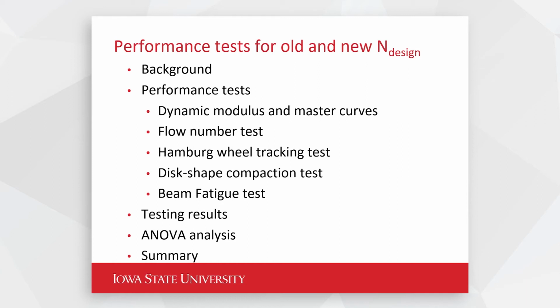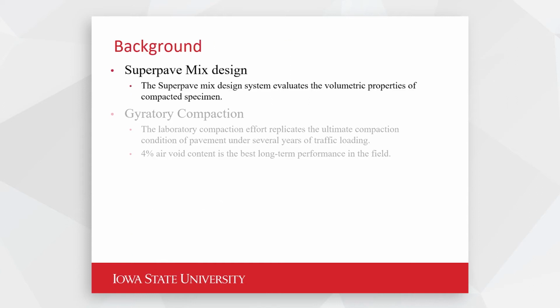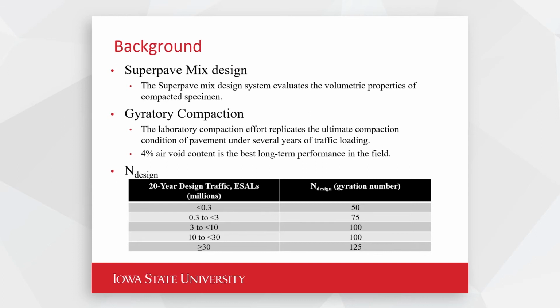And then after that, we were doing some pavement ME. So we won't go into all of the details of how we attain the optimum binder content and all that. That's fairly standard at this stage. But what we can do on the next slide is highlight the new design levels. And so we were seeing, as an example, on the low volume roads where it's less than 0.3 million ESALs, the gyration effort was reduced from 75 gyrations to 50. Okay. And so we see this as a more consistent compaction criteria, and we anticipated seeing improved performance.